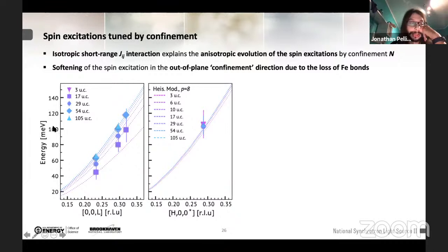So I'm showing the dispersion relation as a function of momentum along the in-plane and out-of-plane directions for different thicknesses. So you can see that in the out-of-plane direction, this simple short-range J interaction was able to explain the softening of the spin excitation. And this model was also able to explain the invariance of the spin excitation in the in-plane direction.